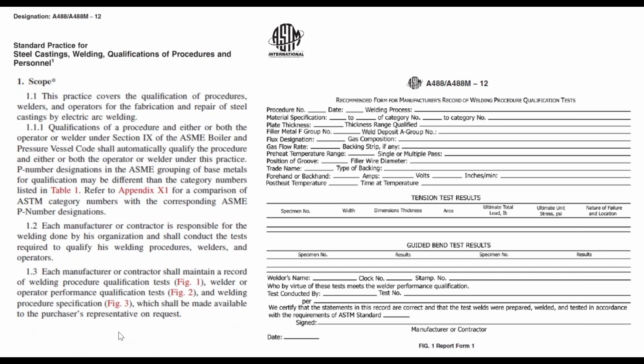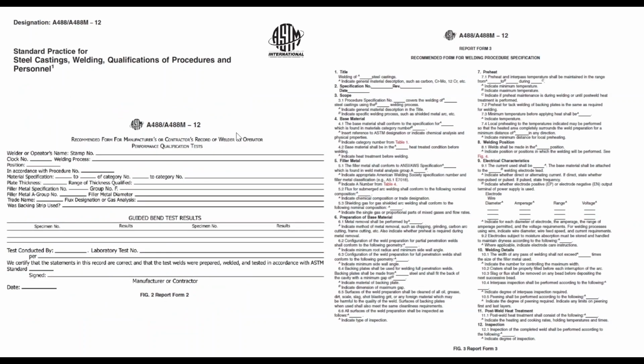So if you want to know if the foundry is capable of making your parts and you're concerned about them using welding as part of their ordinary production practice, you have every right to ask for and receive copies of, or at least examine, their welding qualification. This is the recommended form for the weld procedure qualification, the PQR. This is the recommended form for the qualification of the welder. This is the recommended form for the weld procedure specification, all in ASTM A488.